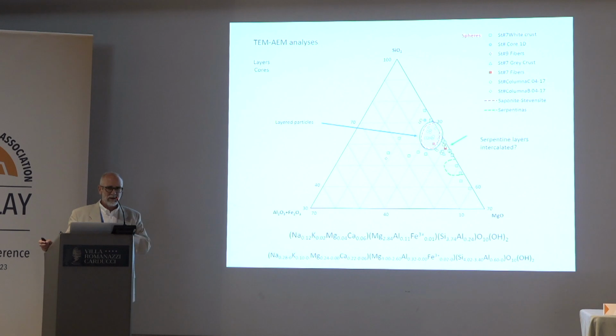We analyzed with a microscope about 100 spots in different samples. I plotted here in this ternary plot, having the silica, the dioctahedral, and the trioctahedral component.